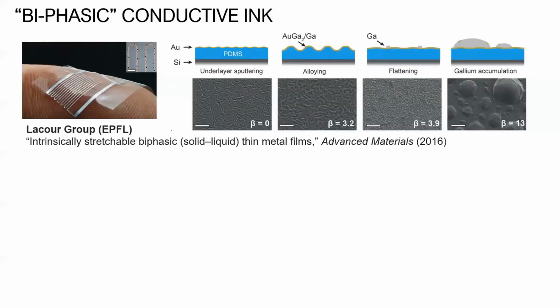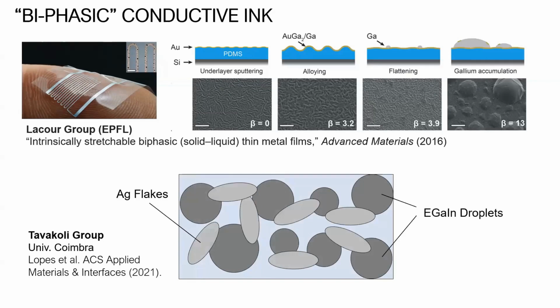So the solution is to again start working with the liquid metal. This is an approach that builds off of something else that Stephanie Lacour had pioneered, that she didn't get a chance to talk about in this morning's presentation, and that is these so-called biphasic architectures, where she has the liquid interfacing with, in her case, gold, on a rubber substrate, and not too unlike what I showed earlier with our laser patterned electronics. What we're proposing is a very different type of biphasic architecture.